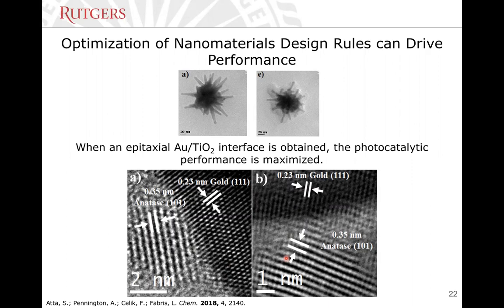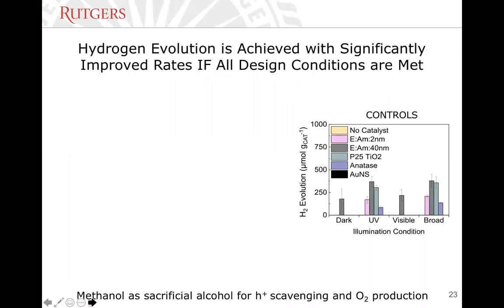So now we have these nanoparticles designed, as we said, with gold nanostars where the hotspots, the spikes, can generate hot electrons. We have a crystalline TiO2 shell that grows unhindered on the nanoparticle, and it's thin. So if we are able to absorb radiation, we should be able to extract the hot electrons into the surrounding environment. So we decided to run these reactions.